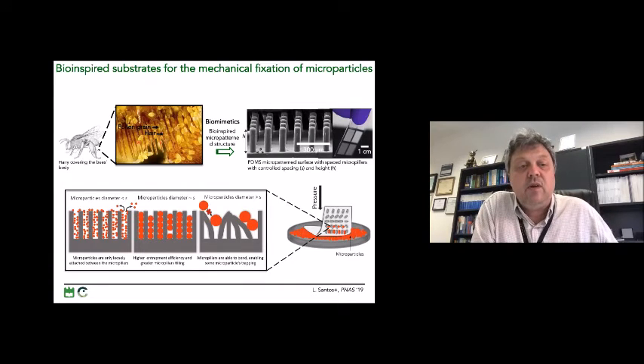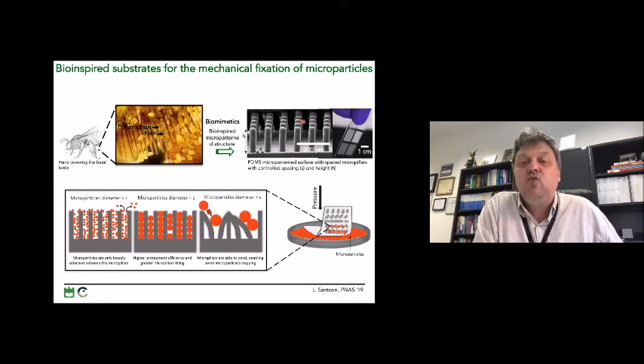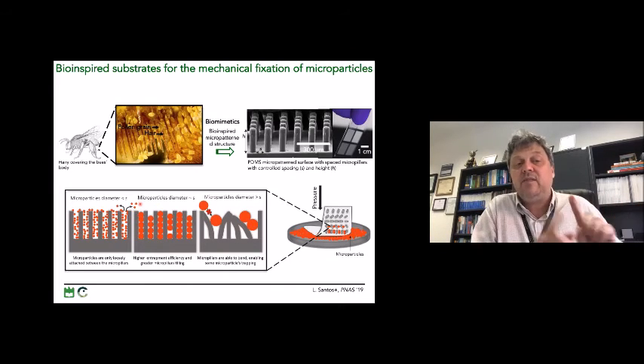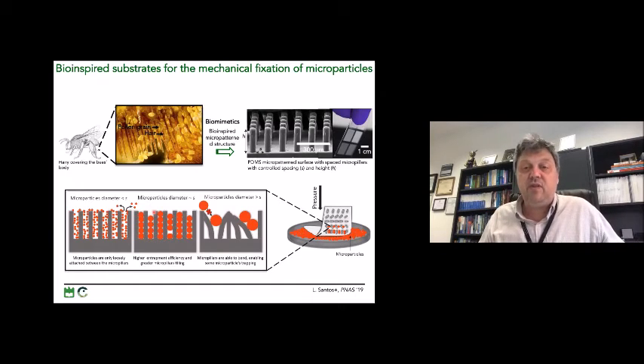So from the observations of the bees and the pollen that are fixed naturally, we prepared biomimetic membranes, also composed of this topography, that we expect could allow for purely mechanical fixation of micro objects. These membranes were processed by photolithography using PDMS to obtain flexible supports. We hypothesized that particles smaller than the distance between the pillars will not be able to fix, due to the lack of mechanical locking. Bigger particles could block the fixation of other particles, so the number of particles that could be grabbed should also be small. And again, we could speculate that if the particles have a similar size to the distance between the pillars, we should have a higher efficiency of encapsulation.